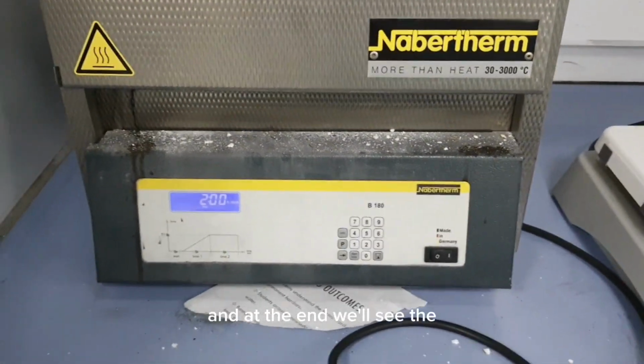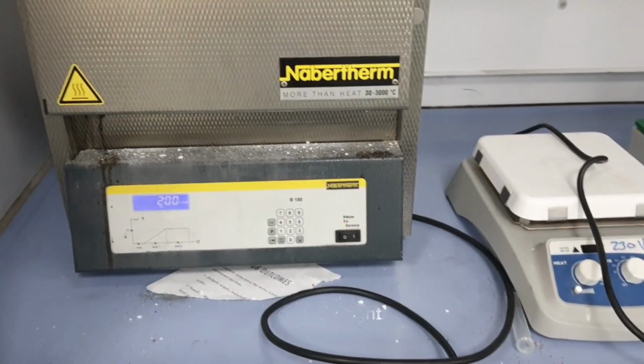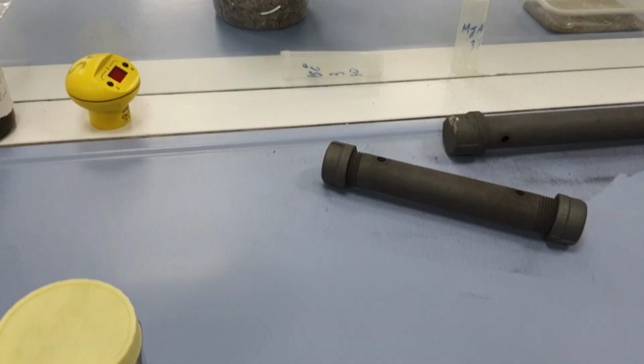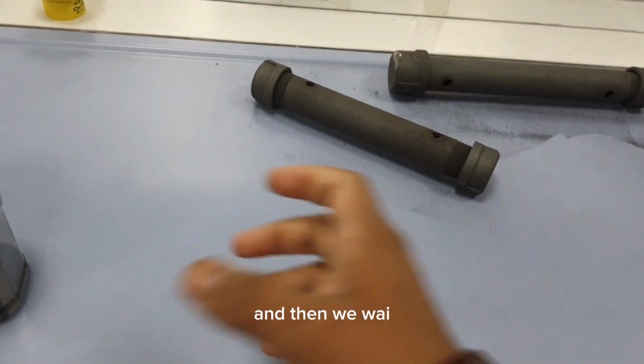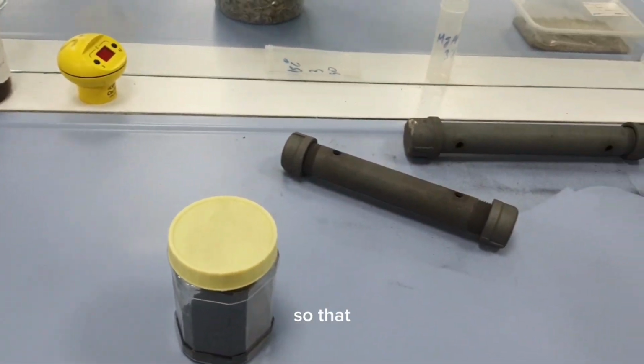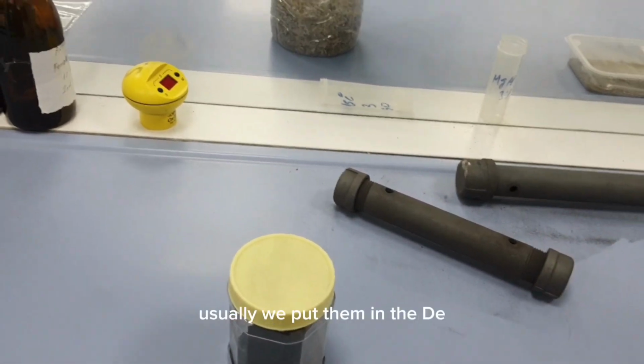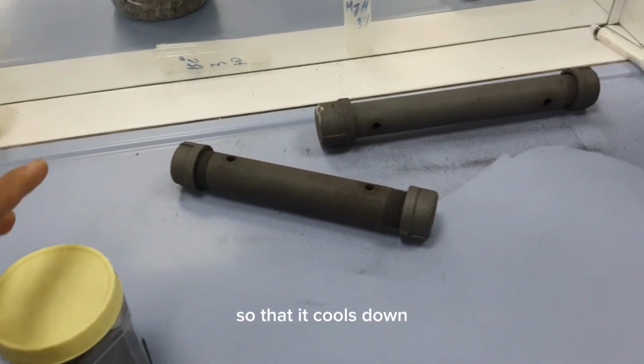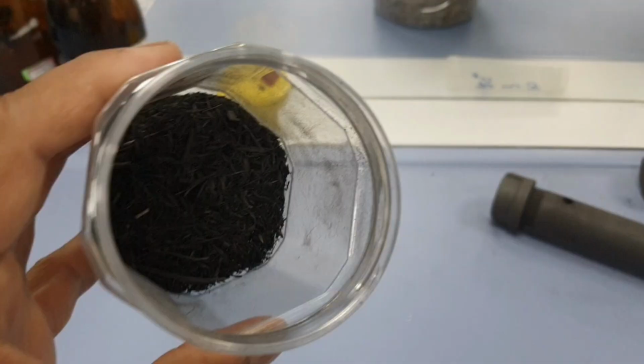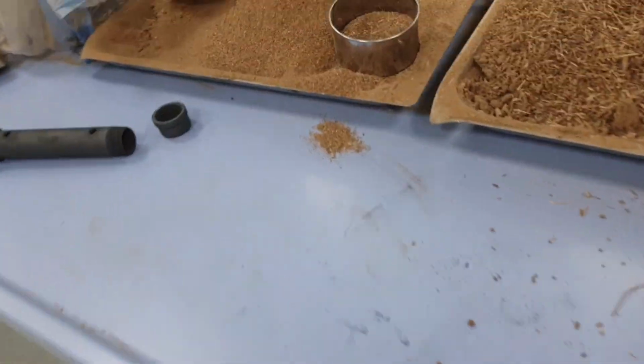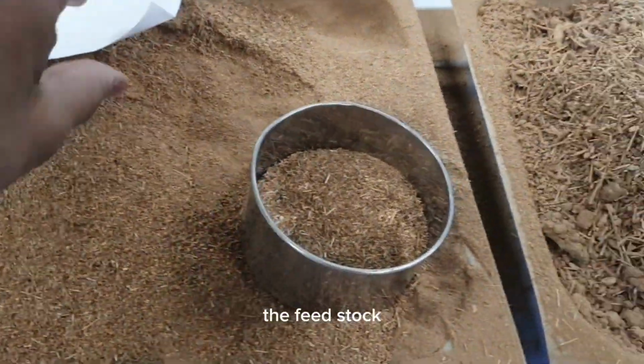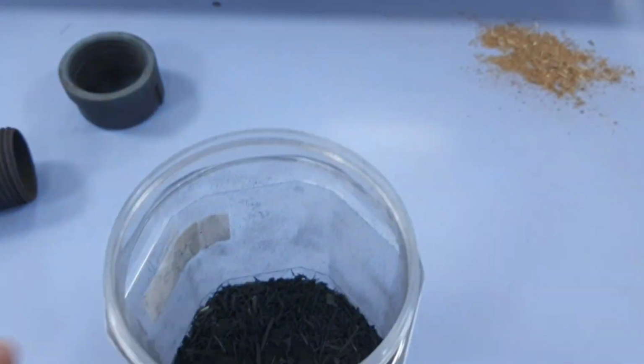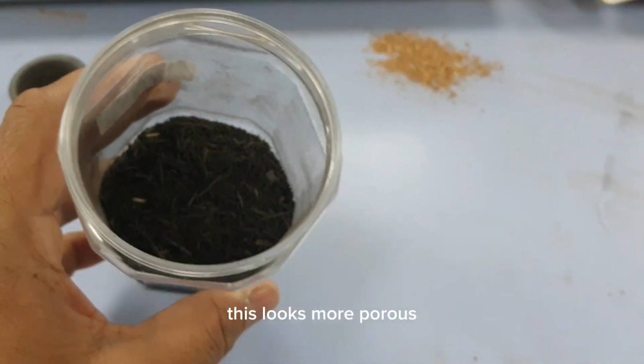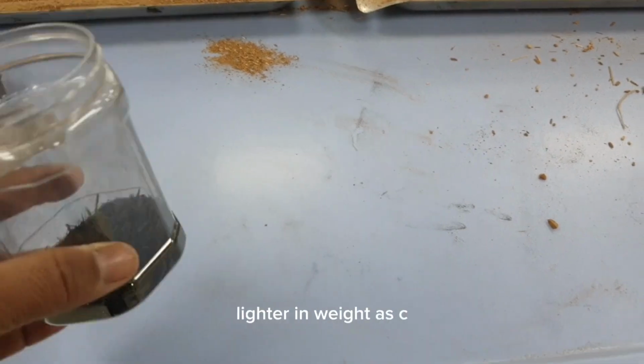At the end, we will see the dry weight. After burning, we usually take out the tubes and wait for a couple of minutes so that they cool down. Usually we put them in the desiccator so that they cool down. Then after burning, you can see the biochar looks like this. This is the raw feedstock, and this is our final product. It looks more porous and lighter in weight as compared to the raw material.